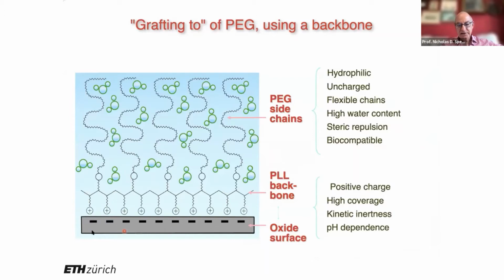If the positive charges see a negatively charged surface, for example, many oxide surfaces, including silicon oxide, the positive charges will stick down and the chains will dangle out into the solution. So spontaneously, we can form a polymer brush by dipping a silicon wafer, for example, into a solution of the polymer. And this is where we started in polymer brushes. And it's also biocompatible. It's resistant to protein absorption, and so a very useful molecule.